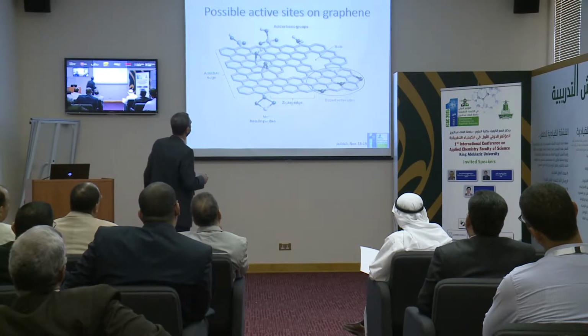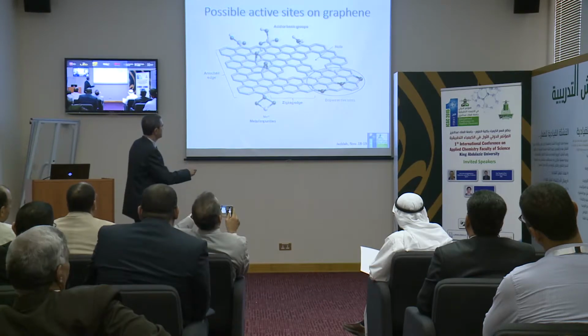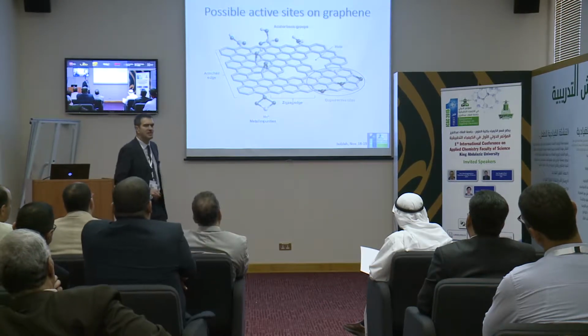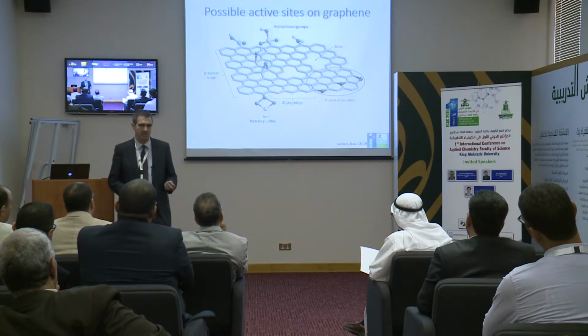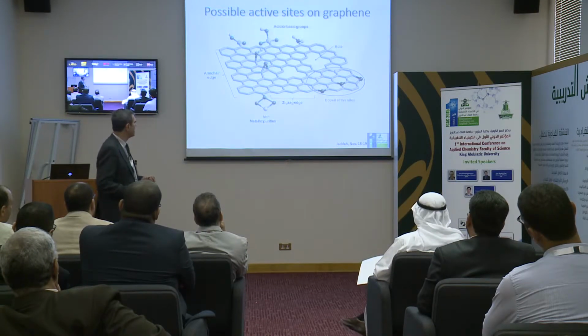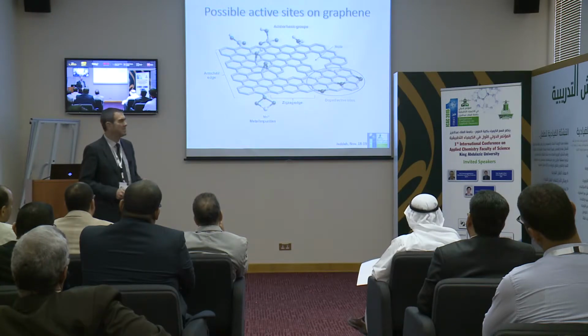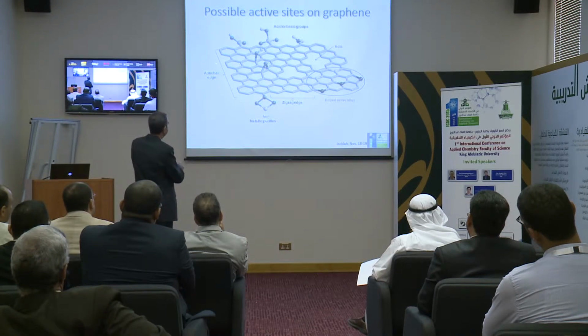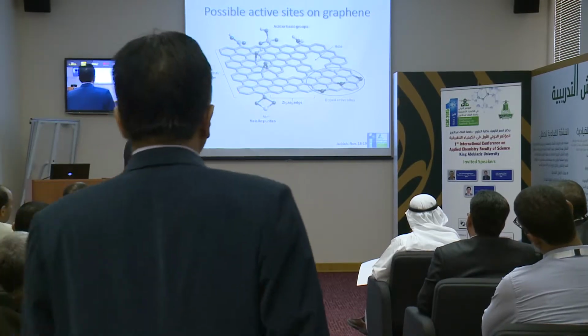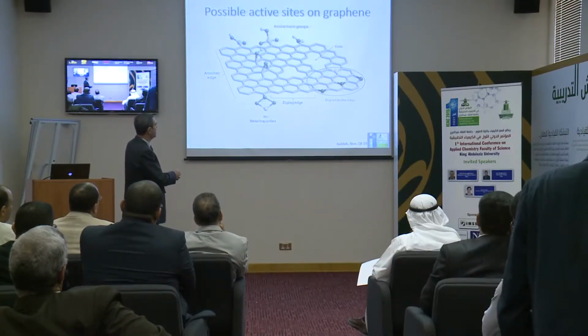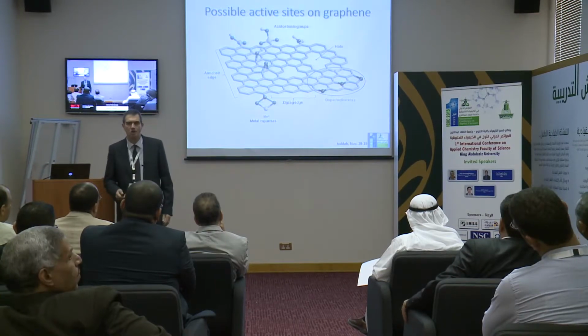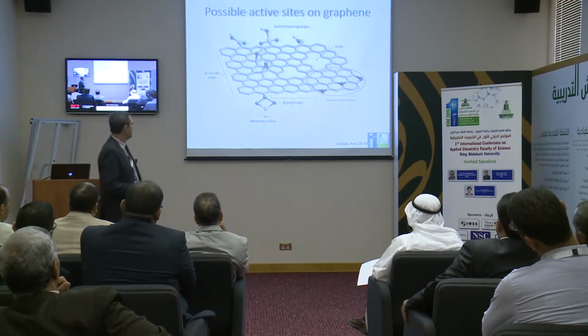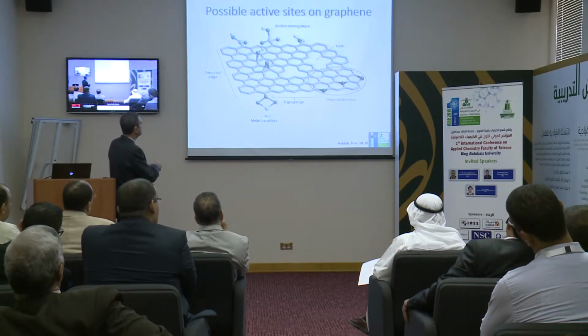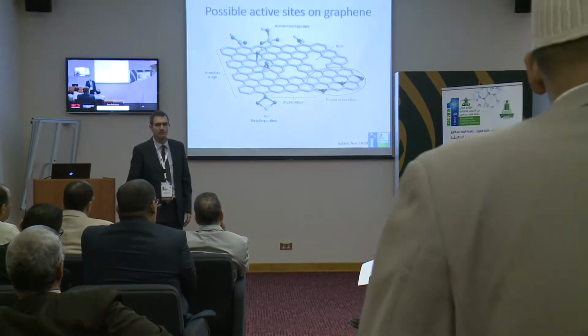So how can we introduce active sites on graphene? This represents a single layer of carbon, and what happens is that when you have ideal graphene, there are no sites, but most of the graphenes that we are preparing have some defects, and defects are really the active sites. For instance, the periphery can be like this, armchair, or the periphery can be in that way, zigzag edges, and the periphery always has catalytic activity. Why? Because this carbon is not fully saturated, so it has unsaturated coordination. For instance, there can be dangling bonds or radicals, so these are really active sites.